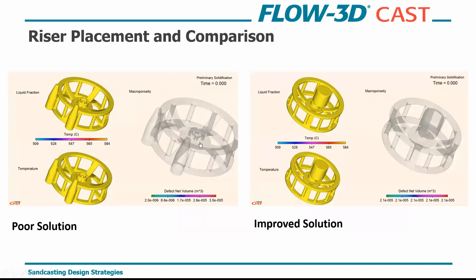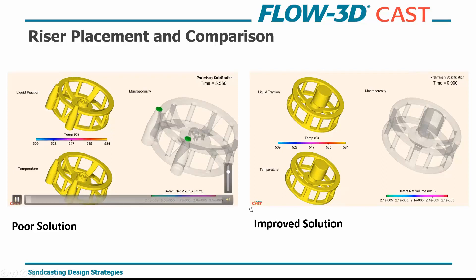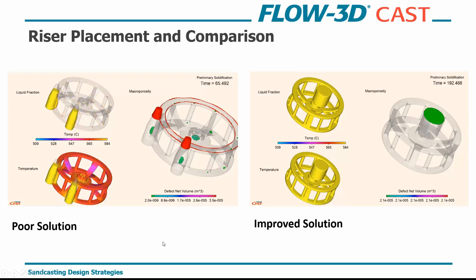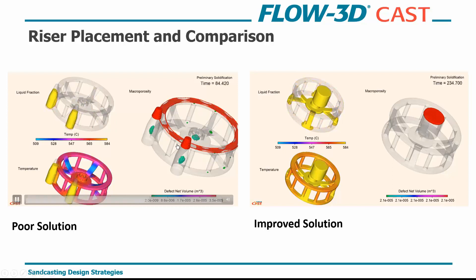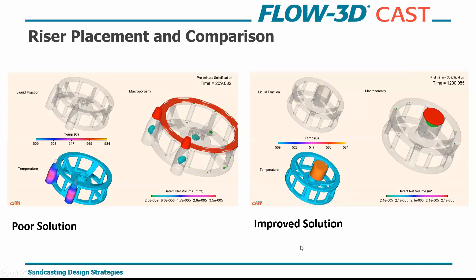Context files mean two different simulations share the same visual output in a one-click operation — once created, this format can be used across any casting and will automatically orient things the way you want to see them. Here are two solutions: risers placed on spokes and one on the center hub versus a larger central riser. With the larger central riser, solidification is much slower, it's the last place to solidify, and we've greatly reduced porosity in the hub and spokes. We'll move forward with this improved solution.